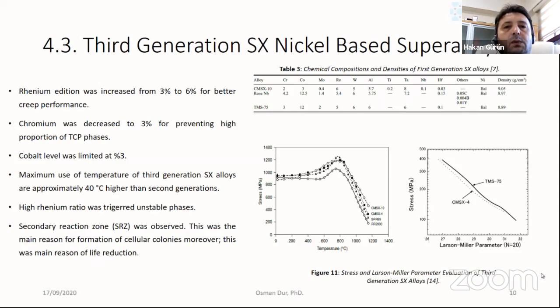Chromium was decreased to 3% for preventing a high proportion of TCP phases. Cobalt level was limited at 3%. The maximum use temperature of the third generation alloy is approximately 40 degrees Celsius higher than second generation. High rhenium ratio triggered unstable phases. Secondary reaction zone was observed. This was the main reason for formation of cellular colonies. Moreover, this was the main reason for life reduction.